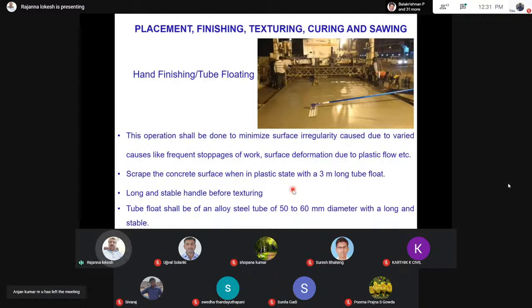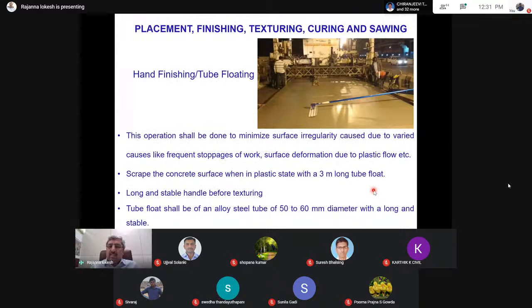Then the placing and hand finishing. This operation shall minimize the surface irregularities that are obtained due to delay in production and placing of concrete. It so happens that it takes around 35 to 45 minutes for a transit mixer to come and deliver. So during that time, a small bump is created where the paver is stopped and where it starts moving again. So using this operation, like tube floating, we press this area using equipment which will be a 3-meter long floating edge with a width of around 0.6 to 0.9 meters, so that